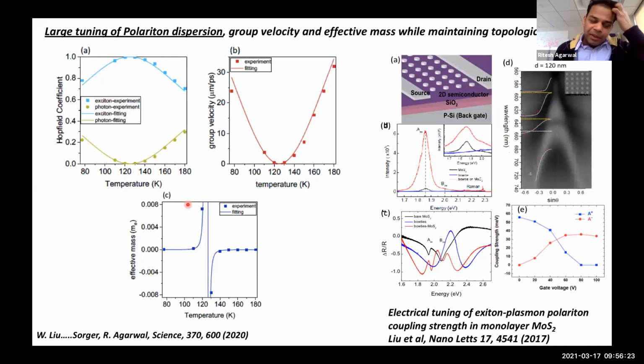So yeah, temperature dependent tuning of these polaritons showed that in the temperature range that we tuned, the topological properties remained intact, which was very promising, that we didn't destroy the topological properties, and the group velocity could be tuned by orders of magnitude within 10 or 20 degrees. So that's really promising, as you can imagine, for tunable topological polaritonic devices.